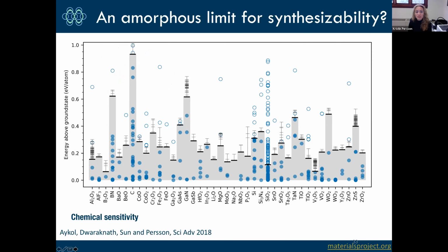And then of course, the skyscraper is your carbon system. The buckyball sits about half an eV above the ground state, and we can still make it because the amorphous state is again so penalized, it hates being amorphous. So that gives you a sense of what kind of classes we can look in for really exciting polymorphism, where we have large windows of metastability.